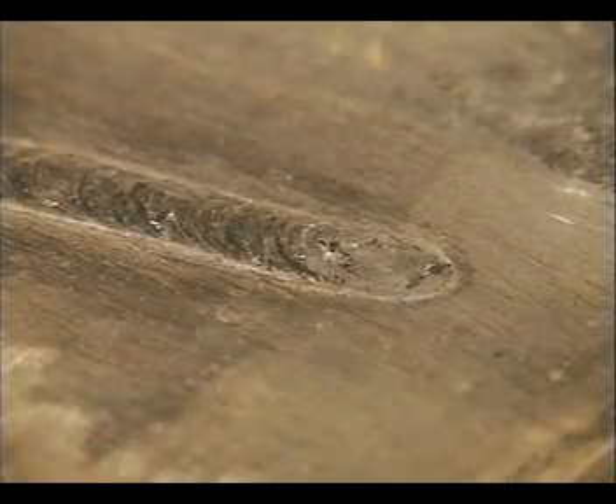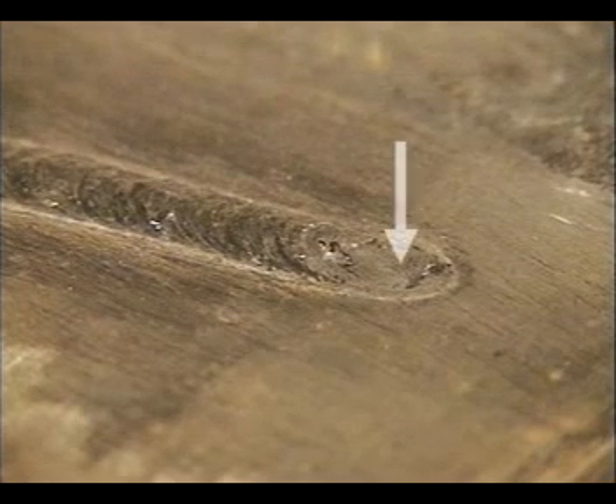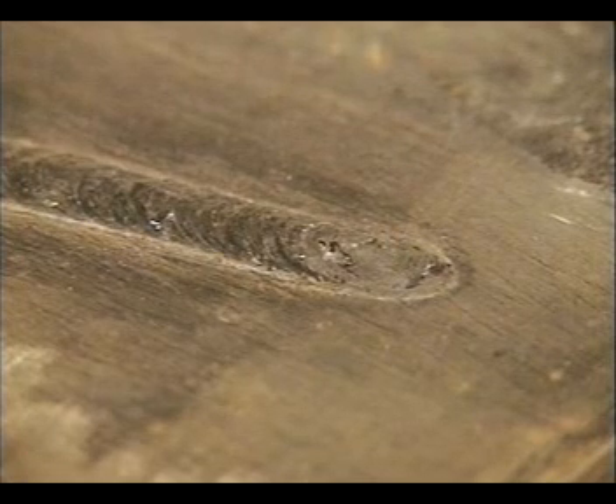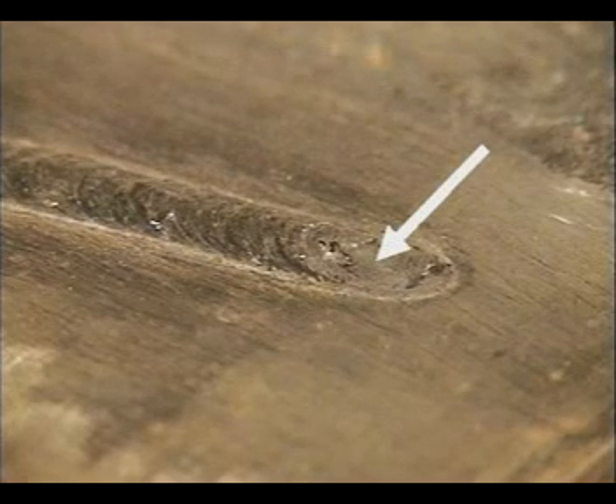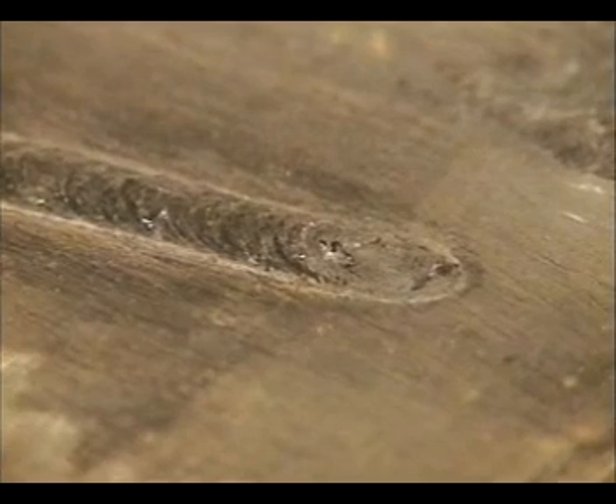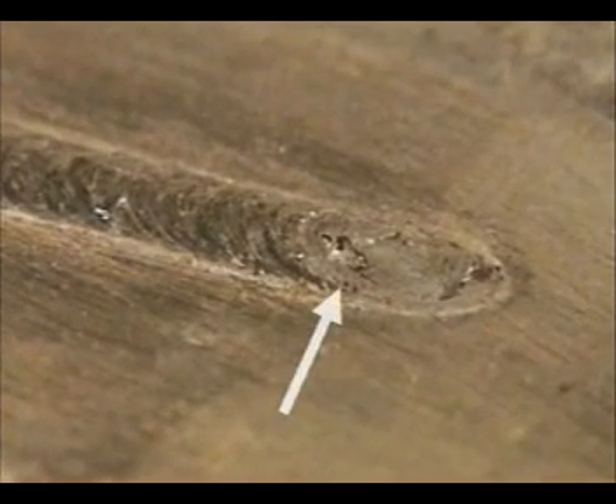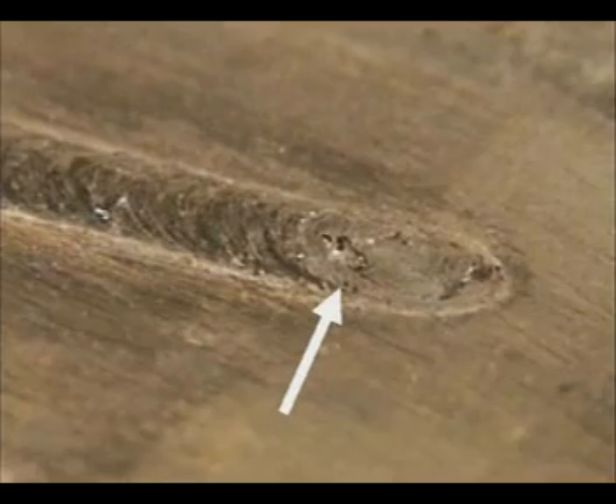When the arc crosses the gap, it melts the base metal, forming a molten puddle. That arc stream also carries the filler metal from the rod into the puddle. This is a 6010 weld bead that I pulled out of quickly. The leading edge of the puddle was actually below the surface of the metal. The strong arc force of 6010 and 6011 penetrates deep into the base metal and pushes the molten puddle back, building up weld bead. While you're welding, watch the sides, right where the weld buildup meets the surface of the base metal. For building up weld bead, either a circular or zigzag motion is commonly used.